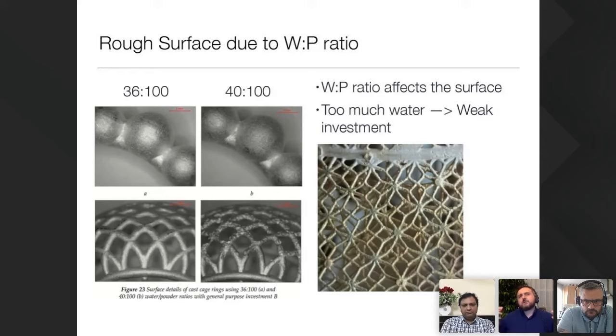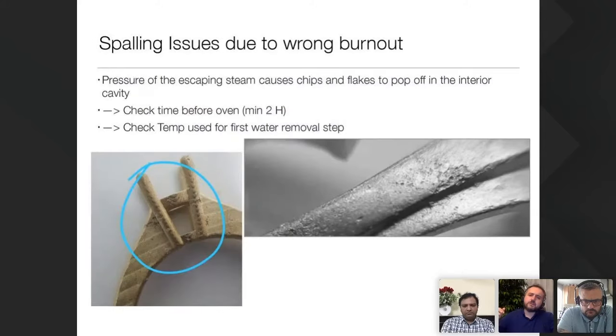What happens is that when the water is evaporating inside the flask, if you have more water, more will be removed from the surface, and this basically gives you a granular surface like that, and we can see it also on the right-hand side. And because your investment is weaker, when the water is removed, it will basically remove some chips and flakes inside the investment, right? This is called spalling,